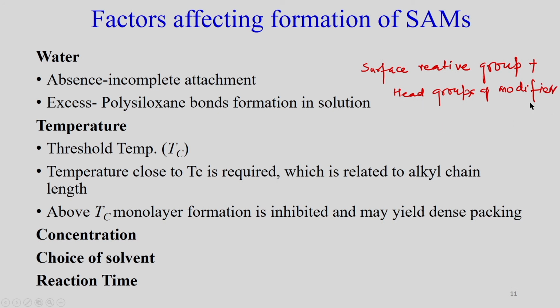As the head group of modifier is also reactive, particularly if you consider the methoxy group or ethoxy group, in presence of water molecules polysiloxane bond formation may take place. It means two silane molecules themselves react with each other to form the polysiloxane bond.